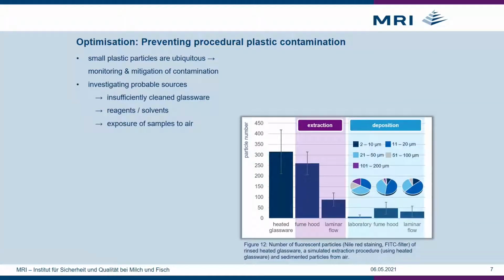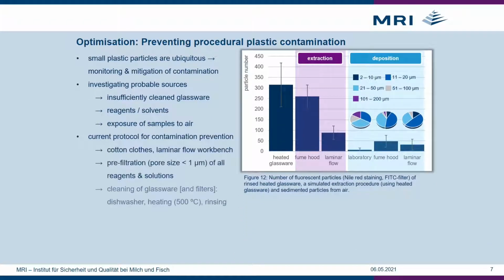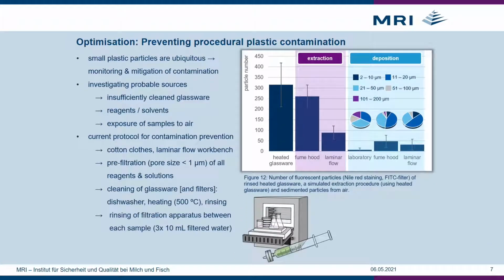During our tests, contribution of particles deposited from air was small. However, working in a laminar flow box was still preferable to working under a fume hood. We had best results regarding prevention of particle contamination when we were working in a laminar flow box and cleaned all glassware, reagents, and filters thoroughly.